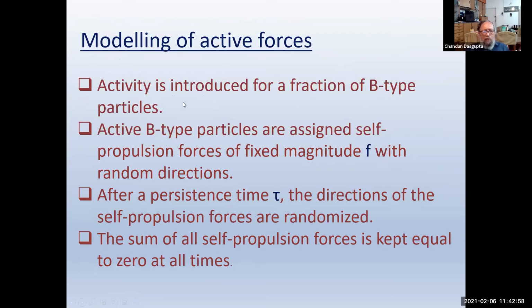And then I have to say something about how you introduce the activity. As I said, the activity is only for B-type particles. And the model that we have here is similar to run and tumble, where the direction of the propulsion force remains fixed for some time tau, and then the directions are all randomized. And then we also make sure that there is no center of mass motion by making sure that the net sum of all the self-propulsion forces is 0 at all times. So again, these are the two parameters: F0, the strength of the force, and tau, the time over which the force continues to point in a particular direction. And then after this time tau, the directions are randomized.